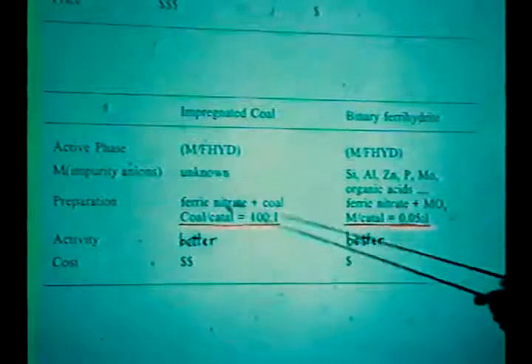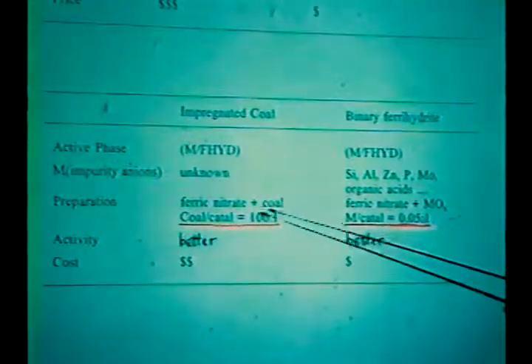Suppose the catalyst loading is 1%, and we want to liquefy 100 kilogram of coal. Then you have to add 100 kilogram of coal in order to produce 1 kilogram of catalyst. But in our case, we just put some secondary element, and this is what we need for 100 kilogram of coal. For 1 kilogram of catalyst, we need 50 gram of impurity anions, and we achieve the same goal. If you think about the difference between 100 kilogram and 50 gram, the saving here is enormous. The activity we found is probably about the same, and the price is of course much lower. In addition, this catalyst has more controllable parameters. Probably we still don't have the best catalyst, but if we can somehow vary the surface composition, probably we'll have a better, active, and selective catalyst.